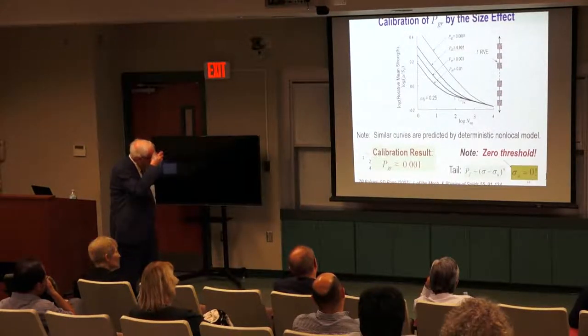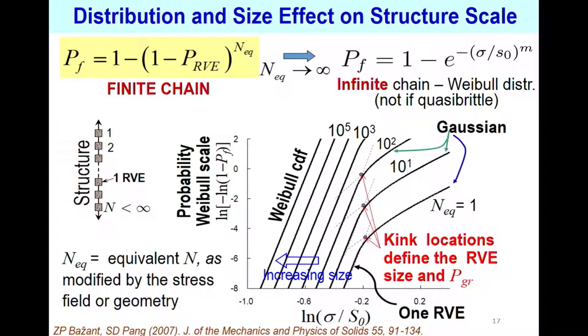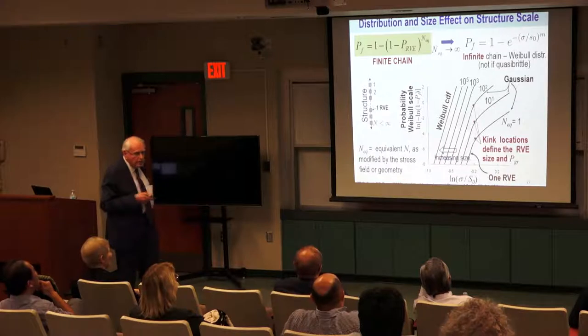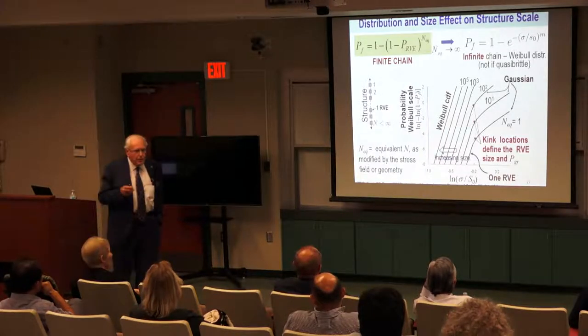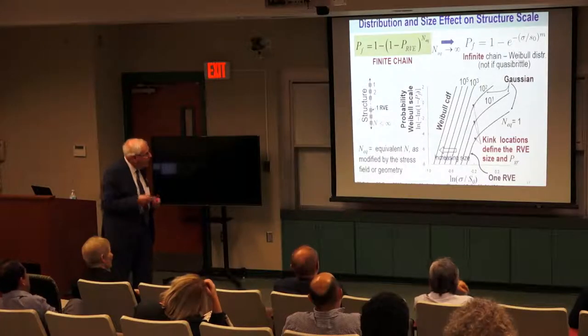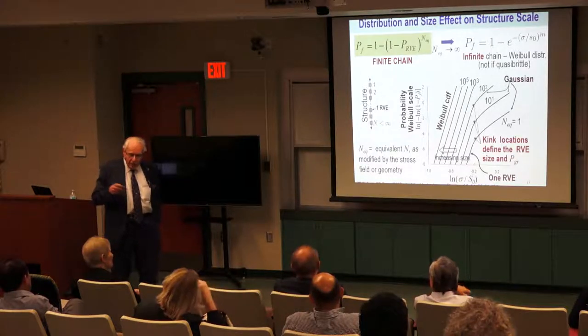Now, there is another interesting point. This Weibull distribution, which is shown here, is typically considered in engineering as sigma minus a constant. The argument is that intuitively we know that for low enough stress it will never fail, right? But do we really need it? If the exponent is typically like in concrete 24, in some metals 30 to 50, and the stress is 1/3 of the maximum, you would need to wait 100 times longer than the age of the Earth for a break to occur. So we don't need a threshold.